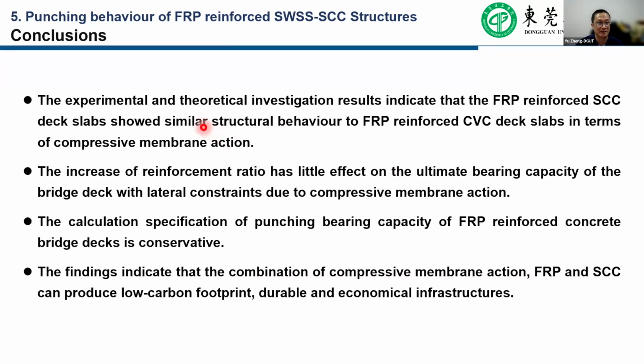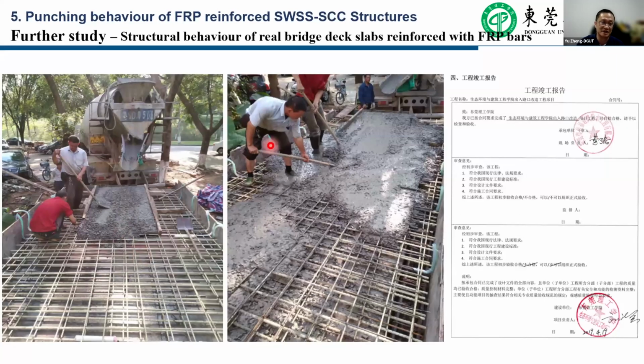Finally, in conclusion, the experimental and theoretical investigation found that FRP reinforced self-compacting concrete shows behavior similar to normal concrete bridge deck slabs. The reinforcement ratio has little effect on the bearing capacity of the bridge deck due to the existence of arching action or compression membrane action. The current design standards are quite conservative, and our proposed models show a good correlation with the test results. For further study of this part, we extend to construction practice.